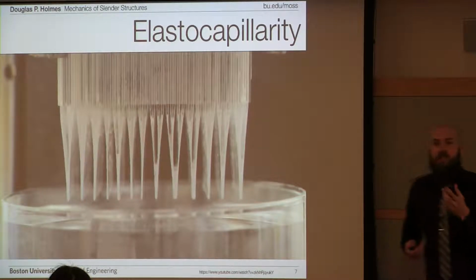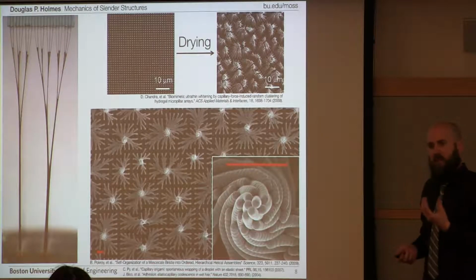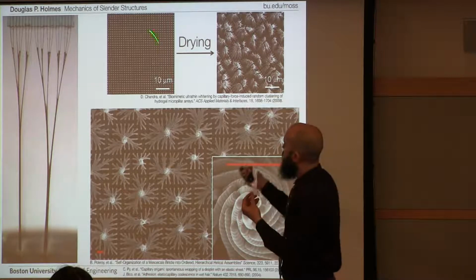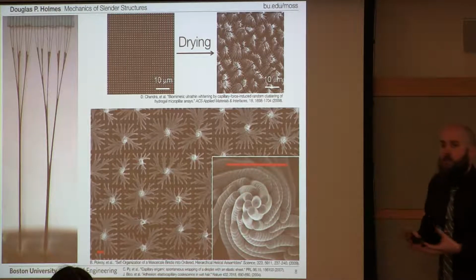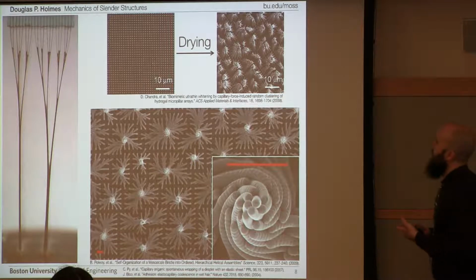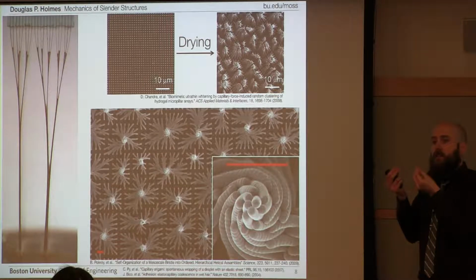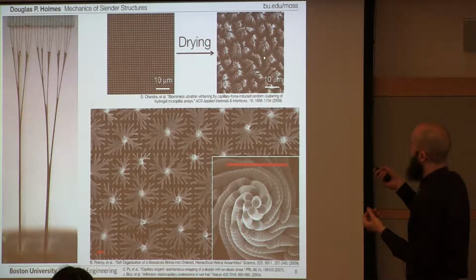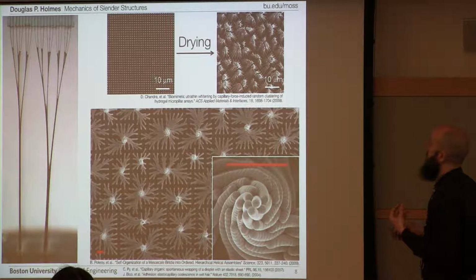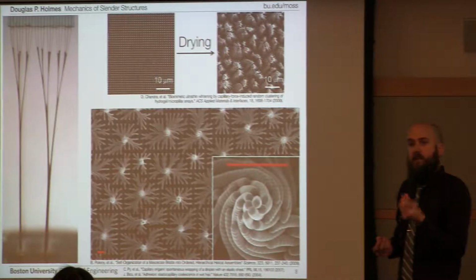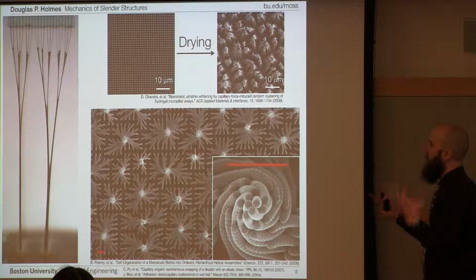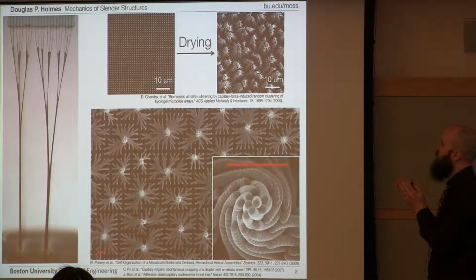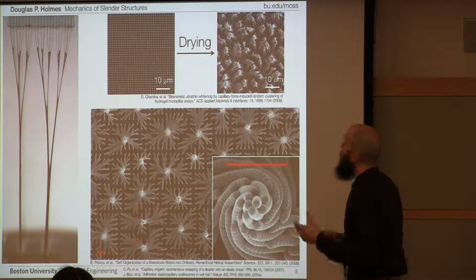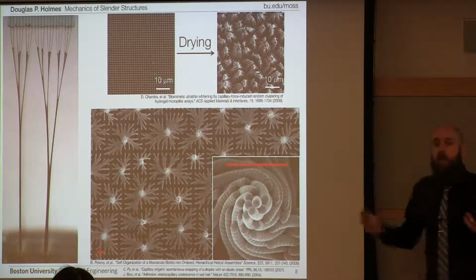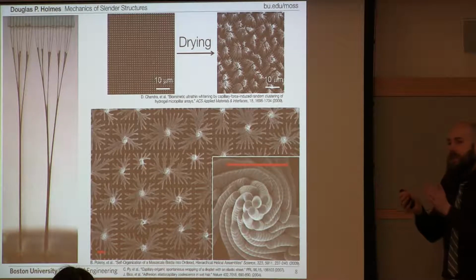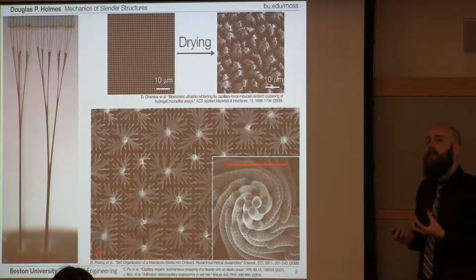And so this is an interesting phenomenon, but it's also a really practically important phenomenon, because for those of you who make micro or nanostructures, and you try to remove your resin from these structures, what you find is that if you try to make really tall, high aspect ratio features, they always collapse upon themselves. And they might collapse in interesting patterns, but nonetheless they collapse, and they collapse for the same physics here, which is this elastocapillary phenomenon, in which elasticity and surface tension combine to bring materials close together. The question we asked was, well, what happens if that fluid doesn't just exist on the outside of the structure, but is able to be pulled into the structure?